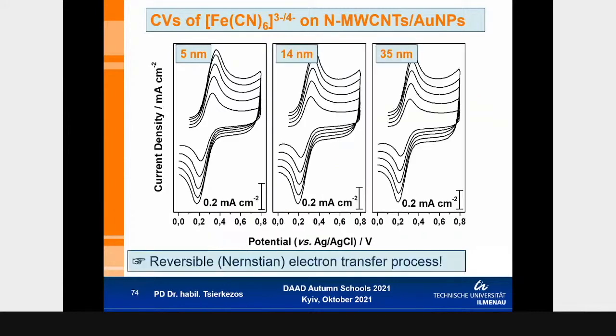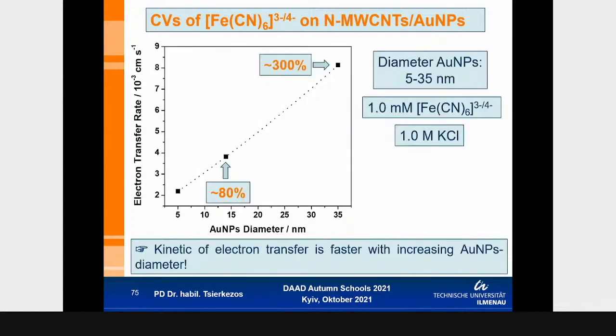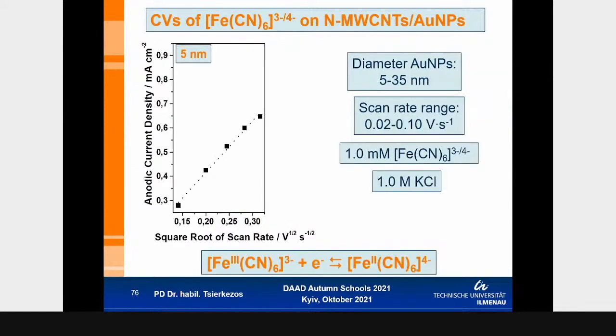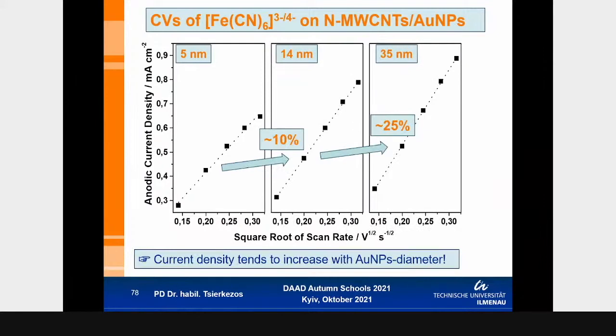We recorded the cyclic voltammograms for the three systems, and we have observed that in all cases we have a reversible behavior, but the kinetics of the redox system becomes faster, up to 300%, when we increase the diameter of the gold nanoparticles, which means that the size of the metallic nanoparticles is also important. You can see that the Faraday current increases up to 25% if we increase the diameter of the gold nanoparticles from 5 to 35 nanometers.